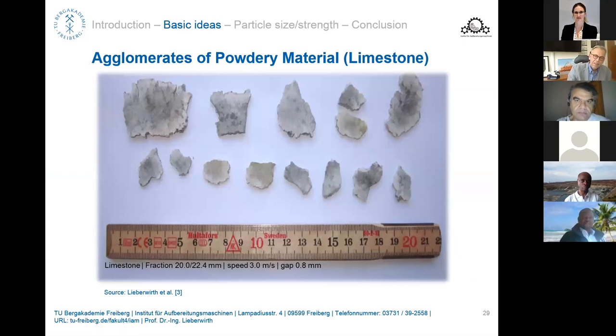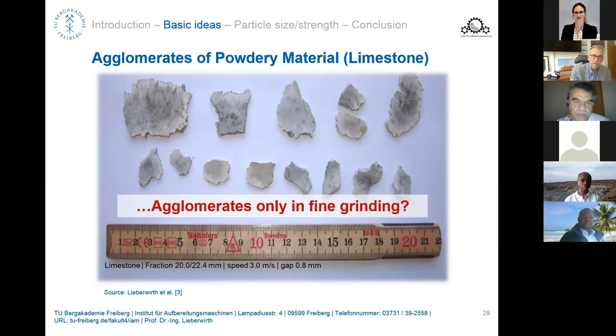And the product of this confined bed comminution is then usually, or in many cases at least, a type of flakes. Depending on the material you are dealing with, the ores, you don't have the flakes regularly or too often. If you're talking about applications of these mills in limestone grinding, then you regularly have these types of flakes. The question is, do you have these flakes only in fine grinding? So the topic today is confined bed comminution. And to produce those flakes, you end up in very high peak loads.